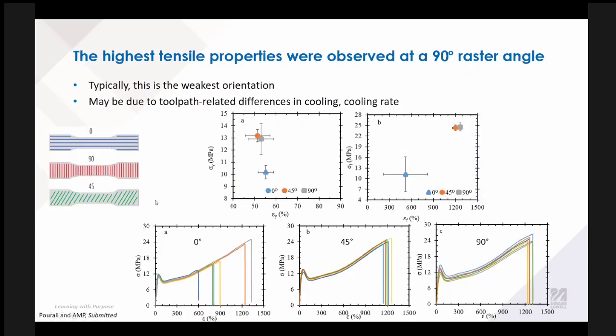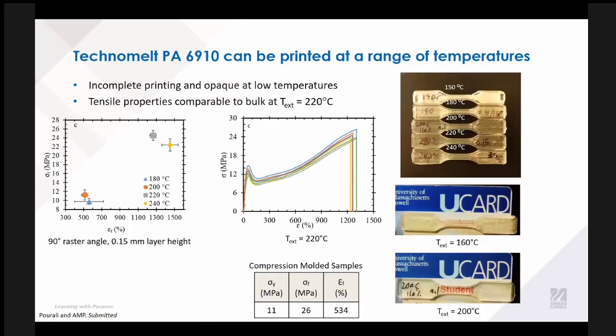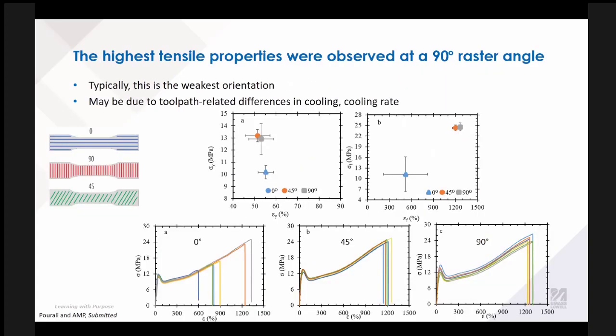One of the other things that is really odd about these materials is that we see the lowest performance in our 0-degree orientation print, where we're filling along the road length. Typically the 90-degree orientation is the weakest because that's where you're filling along your weld lines. But here we see that our 45 and 90 have better properties than the 0-degree, which is something really odd. The properties at 45 and 90 degrees are really excellent, and again are comparable to bulk properties.